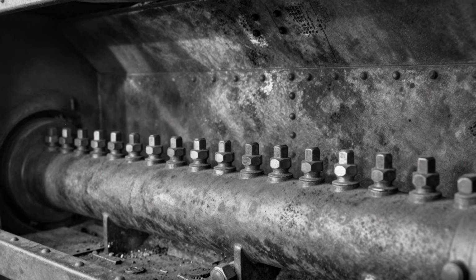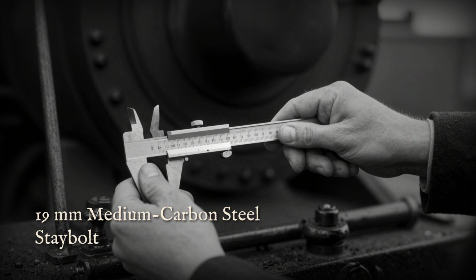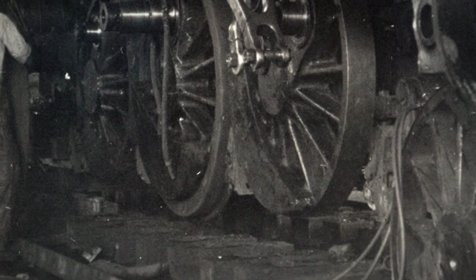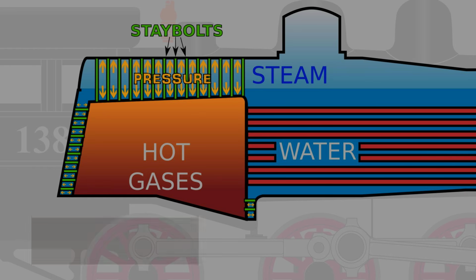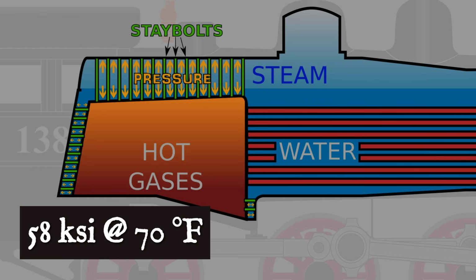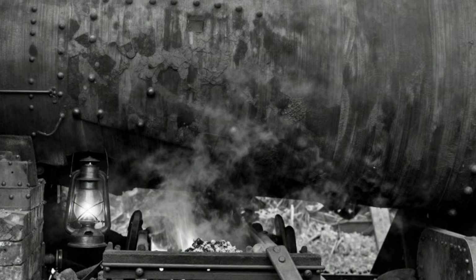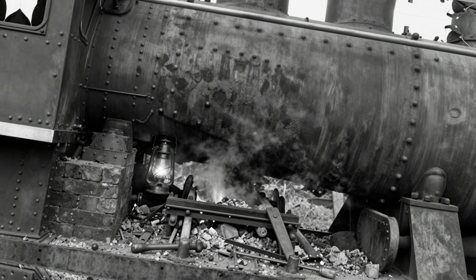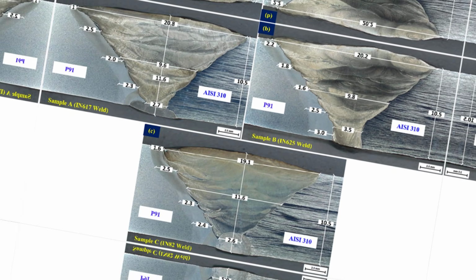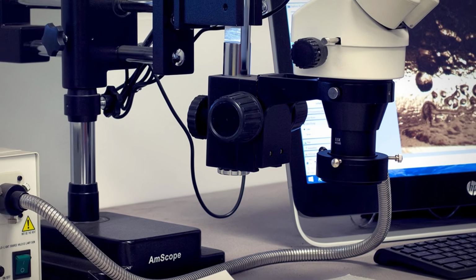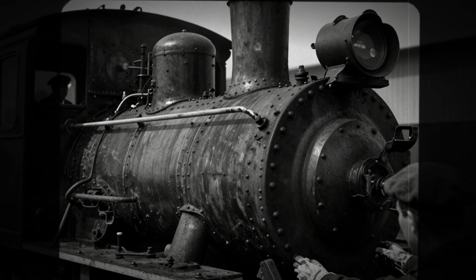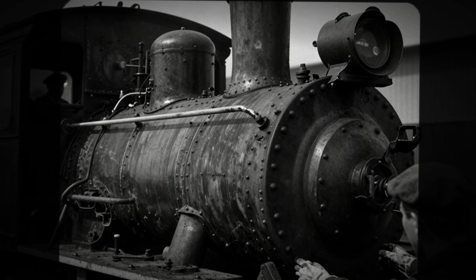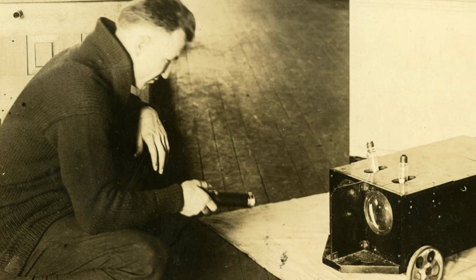Staybolts are the next to go. Each bolt is a 19mm shaft of medium carbon steel, torqued to hold back the hydrostatic load. The spec sheet claims 58 ksi at 70 degrees Fahrenheit. In the firebox, after years of thermal cycling, that number means nothing. Fatigue cracks form at the thread roots. Every pressure cycle is a hammer blow. Beach marks crawl across the fracture face, visible only under a stereo microscope. The bolt fails in silence. No alarm, no warning, just a faint click lost in the roar of the draft.